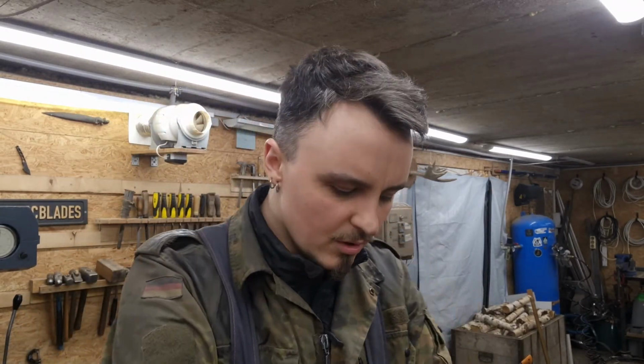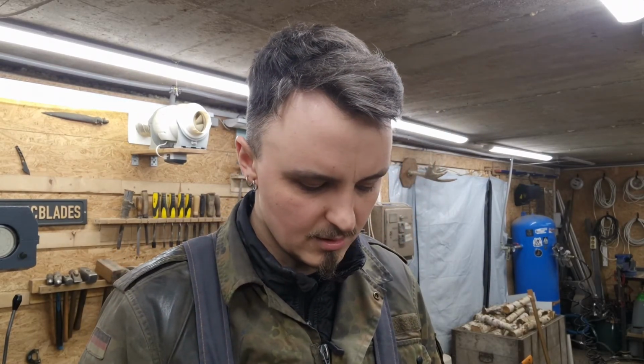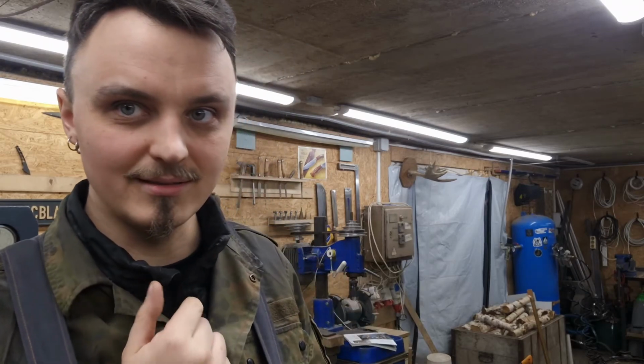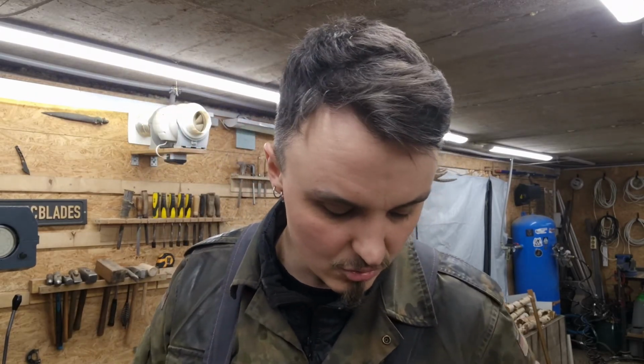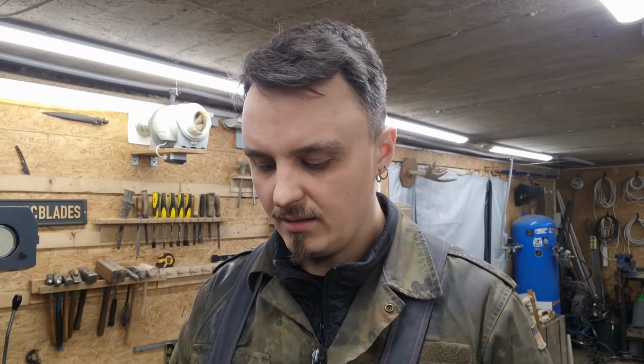That would make sense. Took me way longer to figure out the cloudy finish, because when you do it with the rough grit, you don't see it. It looks pretty uniform, but it's the grit that does the cloudiness. But you only see it when I do the second stage of blasting, which is way smoother, gives you this beautiful crispy texture. But I don't know. So look, you are not learning stuff. I am learning stuff on these vlogs. So I did not manage to grind those, but I'm very happy that I managed to preheat, treat, grind, sandblast, and heat treat these. These will be in annealing the next day for 4 hours with 2 2-hour cycles.